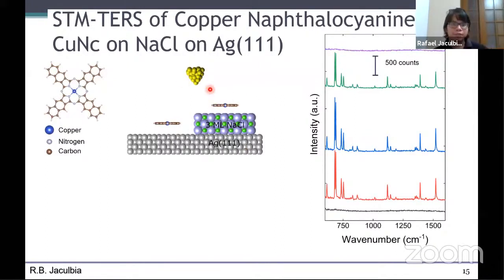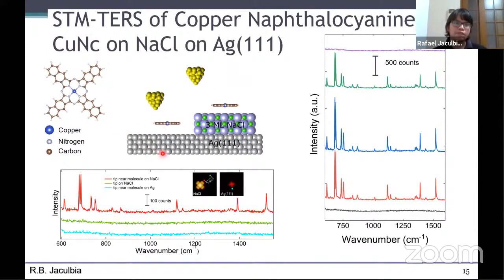Also, surprisingly, we wanted to compare this signal, because this is our technique and this is the usual way to measure TERS. When we place the tip on the molecule on metal, we couldn't find any Raman signal. So it's quite surprising, considering that this is what was previously done. In order to investigate this point, we checked the electronic states of the molecule.